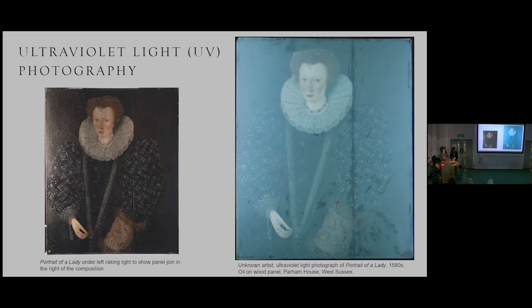So in conservation, we use ultraviolet light to examine paintings to better understand the materials like varnish, paint media, and pigments present. The intensity or color of the fluorescence emitted by the material can help us identify them or possibly gauge whether they have been on the surface for a long time. When looking at the portrait of a lady under UV light, we can see an even green fluorescence throughout. This type of fluorescence identifies the coating as a natural resin varnish, and since fluorescence intensifies as the varnish ages and yellows, it is possible to say that it's been there for quite some time.